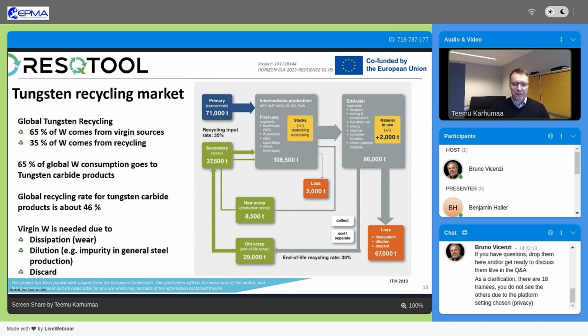And we can see in this graph that the losses, the 65% or something like that, go to losses, dissipation, dilution, and discard. So really high quantities are lost from the global tungsten industry and supply chain. Out of this 108,000 tons, about 65% goes to tungsten carbide products. So the rest is tungsten-containing steels and superalloys and tungsten heavy alloys, etc. And for the tungsten carbide, so hard metal tools, the recycling rate globally is about 46%. And in Europe, I don't have a figure in mind, but I would say it's much higher. It would be 50 to 60%.